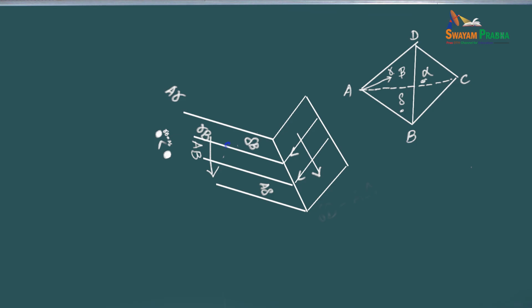So it's a weird vector because it is gamma B. Gamma B, it's this vector here. I'm putting blue. It's this vector minus A delta, which is the vector at the back here. So it's a long Burgers vector, right? It's a long vector. So this segment here has quite a bit of energy. So what is going to happen if this is very expensive? What is going to happen near here? What do you think is going to happen?